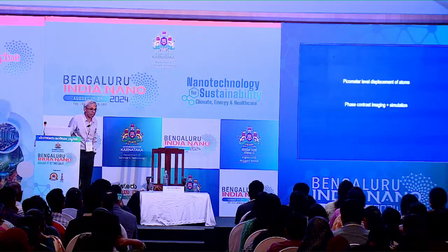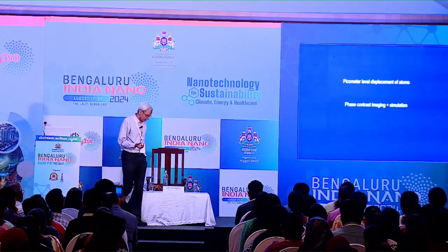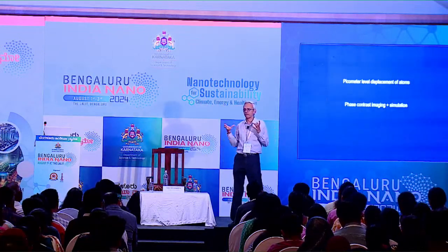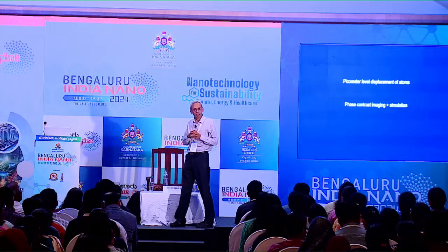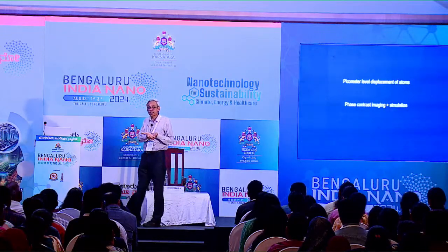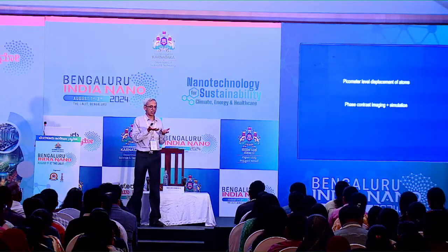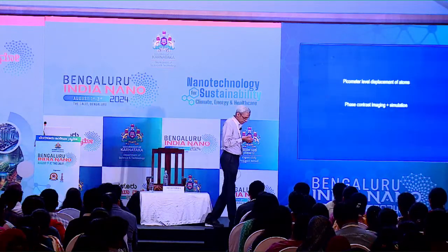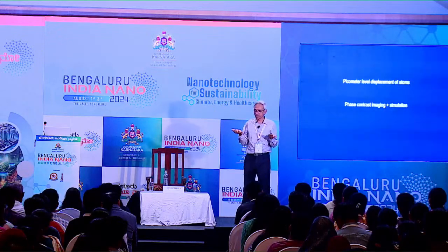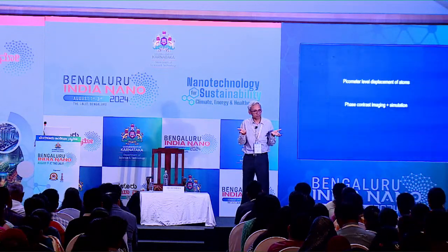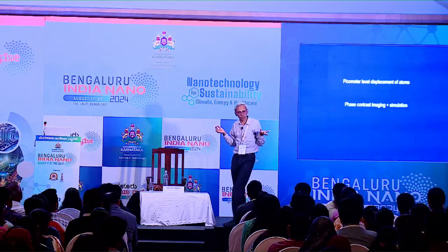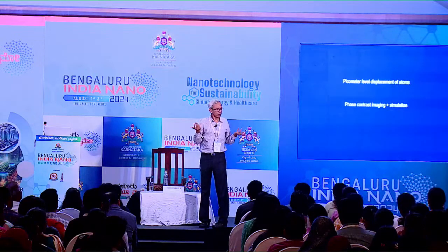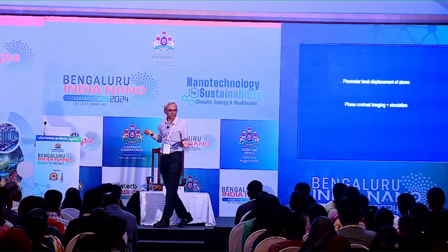So one of the important things about nanostructures, and why such microscopy becomes important: all of you know that when you make things into nanomaterials at the nanoscale, the surface becomes a significant fraction of the atoms, typically 70%, 80%, 90% of the atoms reside on the surface. Surface atoms obviously have lower coordination. They're not surrounded by atoms all around, which means that the structure is not the most stable structure. Therefore, atoms can move or relax to form a lower energy structure.